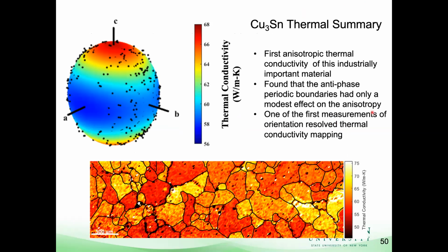So to summarize this copper 3 tin work, we made the first anisotropic thermal conductivity measurement of this material. And we found that antiphase periodic boundaries had only a modest effect on the anisotropy. I didn't mention this, but this is also a relatively new technique. Being able to map the thermal conductivity, then relate that to the orientation dependent thermal properties has only been done once before in the literature, as far as I know. So this is also a quite novel technique.